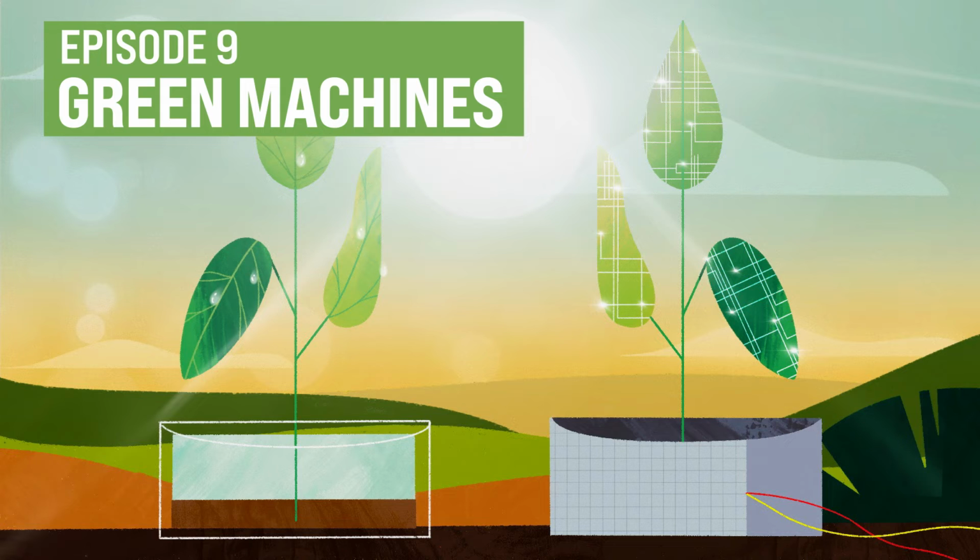Another difference is that we can also change the way that the semiconductors absorb by changing their band gaps, the energy that a photon needs to have in order to be absorbed. And the energy of a photon depends on what part of the electromagnetic spectrum it's in. Silicon and other semiconductors will have a so-called band gap, and when the photon energy is higher than that band gap, it's absorbed. Some semiconductors have a band gap in the visible. When you hold them up to the light, you can see that they absorb some photons and let others through, and that gives them a color.